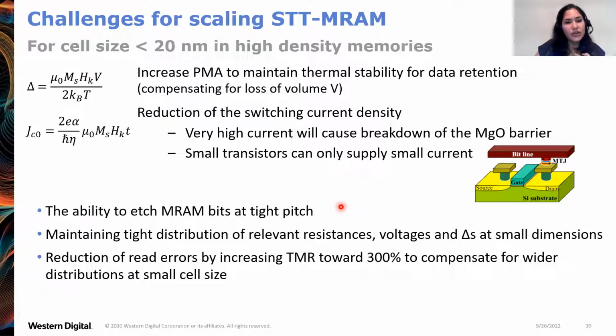How do you make these very small MRAM bits, 20 nanometers or smaller, and do that at tight pitch, as needed for a high density array of bits? And to do that while maintaining tight distributions of these various performance parameters that I described. So for example, when you have very small bits, you can expect wider distributions from these small sizes, and so these wider distributions will lead to read errors. So we want to compensate for that by making the read signal really high, which means TMR needs to be even higher than what we have now in products.